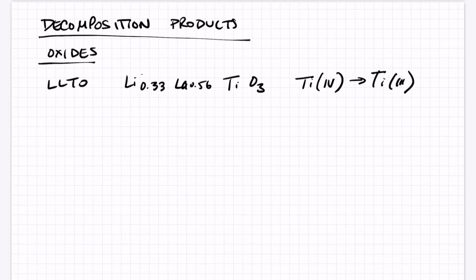And in fact, at the nanoscale, if you try to produce titanium dioxide, TiO2, you will produce that. But at a certain size, as in you go small enough down to 10 nanometers and such, there are certain facets that will stabilize titanium 3+, and in fact, titanium dioxide, the titania, shows up more as a bluish color as opposed to the white that you often expect of titanium dioxide, okay?